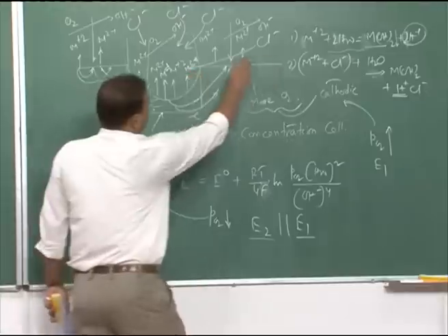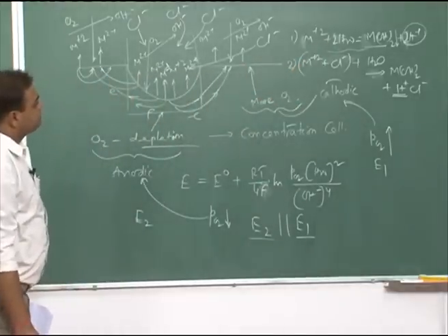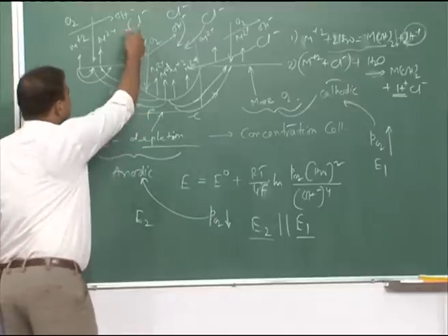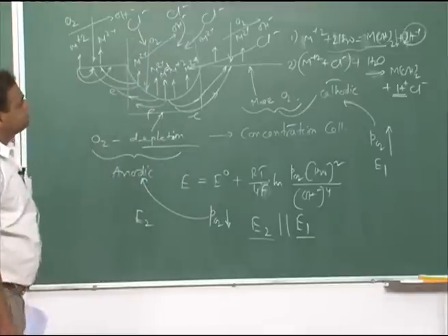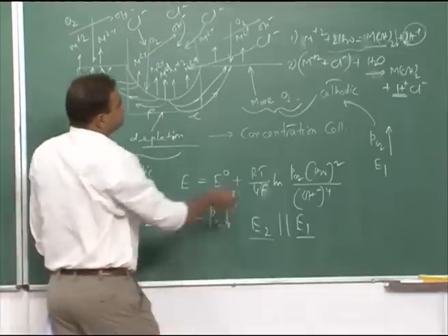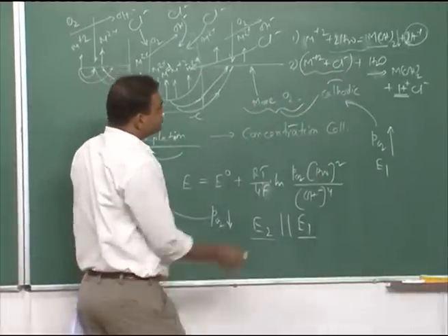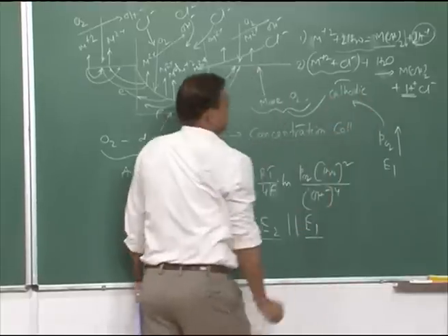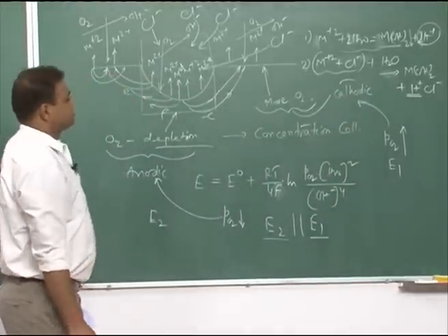These ions hydrolyze in the presence of water, form H plus ion, and chloride ion would come here to neutralize all those extra positive charges, and then that metal chloride salt forming there would also hydrolyze and form acid. And of course, there would be chloride ion concentration also.